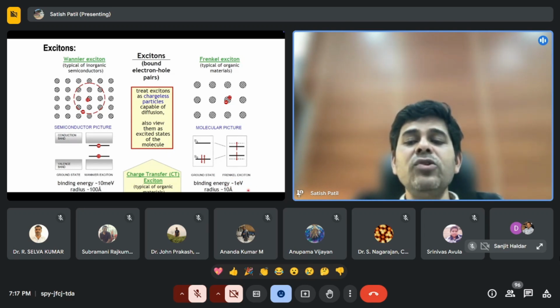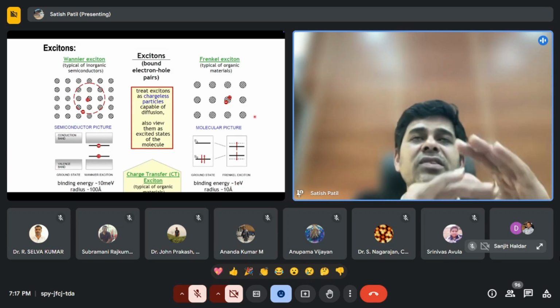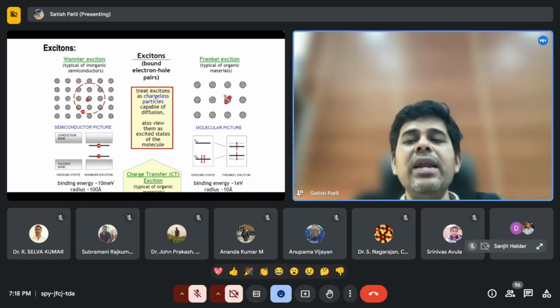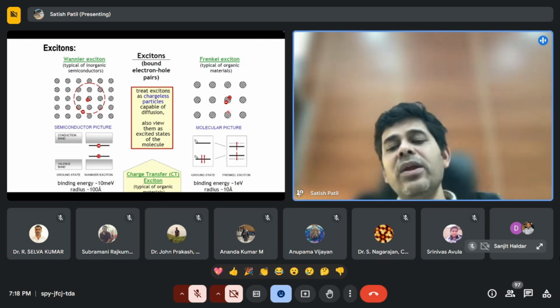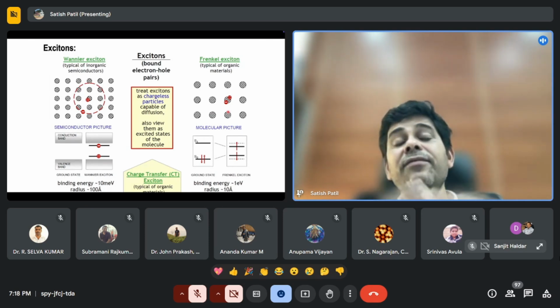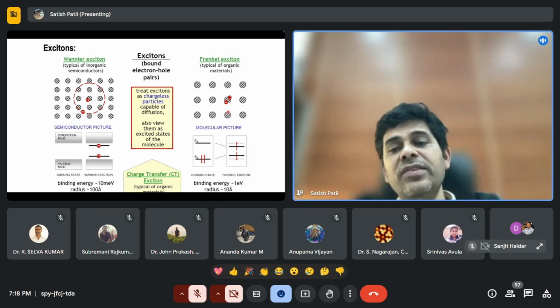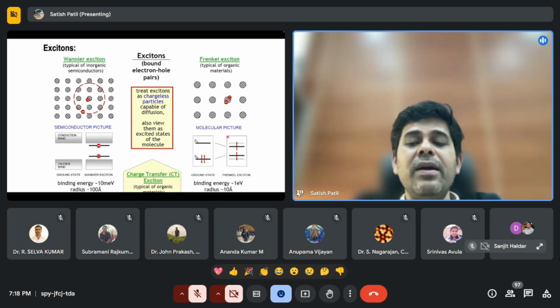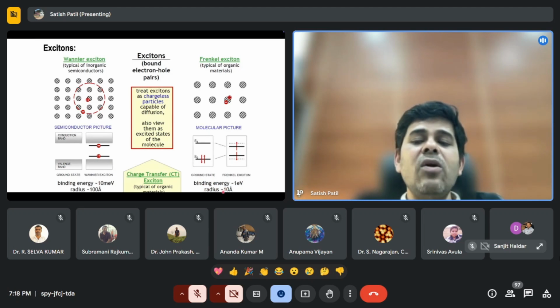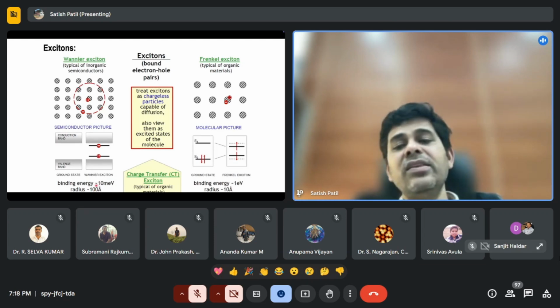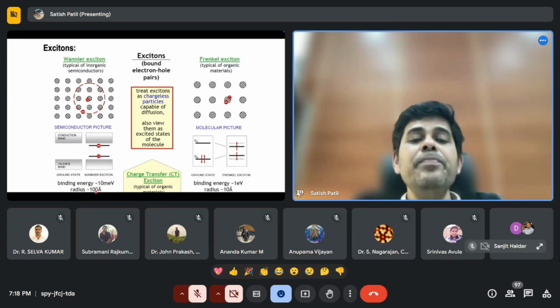So it's not possible to separate hole and electron in case of organic if you use just a single layer of a photoactive layer and make a device. They recombine, not separate out, and you cannot make very high efficiency solar cells by using a single layer of organic semiconductor. So the radius here is around 10 angstrom, and this is actually 100 angstrom. You see that this is very, very difficult to make, okay? And the best solar cells by using organic semiconductor.